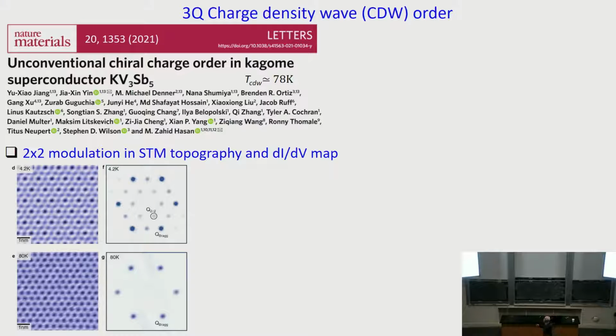So this is STM, right? And if you go above the CDW transition, this material has a CDW transition, potassium one, of 80 Kelvin. So you go above that, and you look at the topography of the surface, and you see it's like this. You do a Fourier transform, it shows 6 Bragg peaks, nothing else. We know this is a great crystal, and we know what to expect from that.